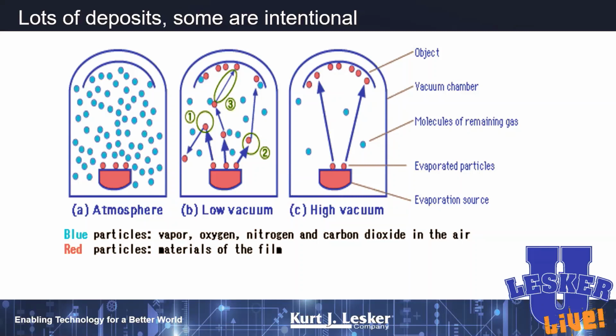So if we think back about mean free path, and let's say this is our source of aluminum here, and here's our aluminum substrate up there, at atmospheric pressure we've got way too many tramp molecules in our system. We have no right to expect that we can generate an aluminum molecule here and that it can travel to our substrate. There'll be too many collisions, too much energy lost. The aluminum metal is going to react with the oxides and nitrides and make anything other than what you want. You'll make no coating at all.